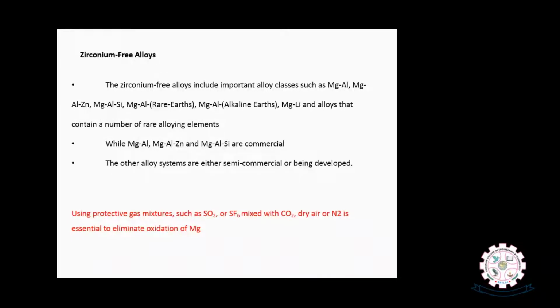Using a protective gas mixture is very important, crucial, in developing magnesium-based alloys or composites by the casting route, such as SO2 or SF6 mixed with CO2, dry air or N2, or the combination of gases which we should use to avoid oxidation of magnesium. Since magnesium is a highly reactive metal, if liquid magnesium comes into contact with oxygen, the oxidation problem is inevitable. So it is not suggested to produce cast components without using an appropriate protective environment.